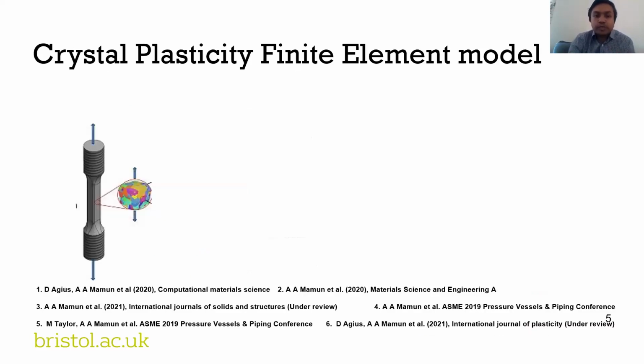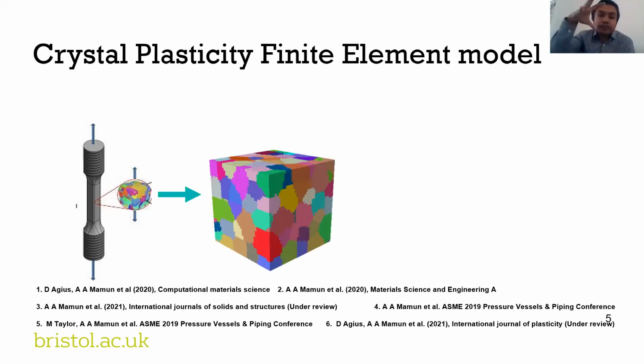So what we do to address this challenge is to take a bottom-up approach in our group. We thought maybe it's more important for us to understand the deformation mechanisms inside the material. For example, how that plastic deformation is affecting the creep deformation, but not just at a component scale, at a grain scale, a much, much smaller scale. And then we can build a model of this material. We can apply some sort of constitutive law, which gives us the deformation within a grain, and that can be built up onto specimen and then to component and so on. For that, we used a special modeling technique called the crystal plasticity finite element model.